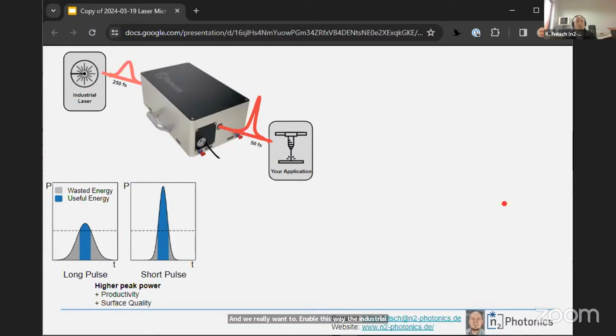Why do we think that going to even shorter pulses gives the user new chances or enables new applications? There are mainly two things that we can focus on, where we're convinced that it gives you a net benefit. The first one is that the ablation threshold is reached more easily. So more of the energy contained within the pulses is above the ablation threshold and actually does work on the workpiece. That means you can run your process either with lower energy and higher repetition rate at the same average power, so you have more productivity because you can run it faster, or you have improved surface quality, as we will see later. I'll show an example there.